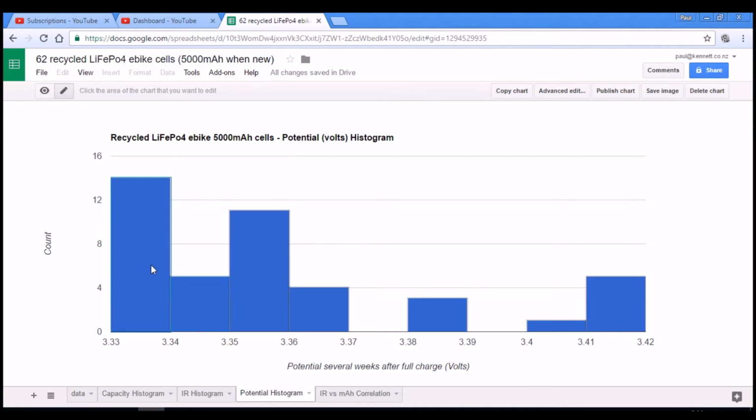but one thing that's interesting, which is the nominal voltage for these cells is 3.2 volts. And so these are all pretty good. None of them were flat. None of them were below 3.2, except perhaps for the ones that were puffy, which I threw out immediately. I did actually measure one, and it had a voltage of 3.3 something. So the voltage was fine, but it was puffy, and that kind of freaked me out. So I threw it out.